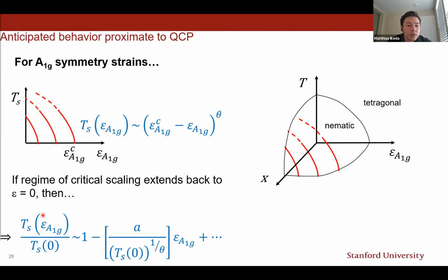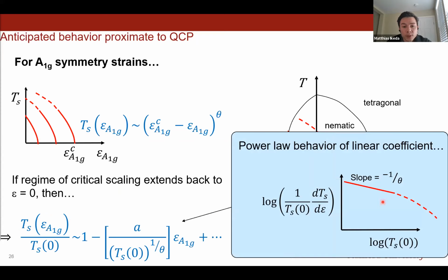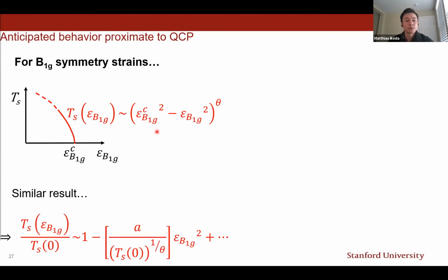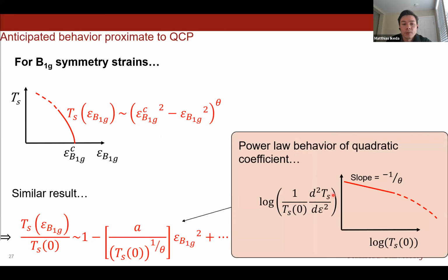Or in other words, if we plot this quantity in a log-log plot versus the zero strain transition temperature, we should find a linear regime, and the slope of this line should be determined by 1 over theta. A very similar analysis can, of course, also be done for the symmetry breaking B1g strain components, but in this case, as mentioned before, by symmetry, the strains have to be squared. And then we find a very similar result, namely that the nonlinear coefficient should also obey the same kind of power law that's governed by the same critical coefficient 1 over theta, resulting in the log-log plot for the nonlinear coefficient, again in a linear function with the same slope.